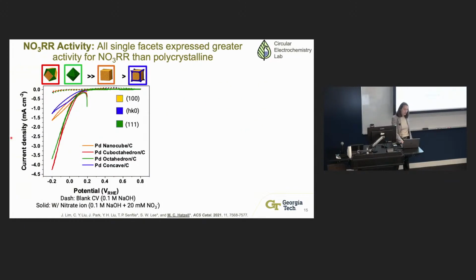And if you're not familiar with electrochemistry, this is an example of a cyclic voltammogram, and generally it tells us a little bit about the activity of our catalyst. So on the y-axis is your current density, on your x-axis is the potential. Ideally, we want to be able to get high current density because that relates to the turnover of the reactant at a low potential because the potential drives our energy up. And here, these dotted lines, which you may be able to see, are the control experiments which have no nitrate in the cell. And the reason why you have to run those is because you can also evolve hydrogen. And so here we want to selectively reduce nitrate, but we don't want to reduce water to hydrogen. And so these show us how much current is going to a reaction we don't want, which is hydrogen.